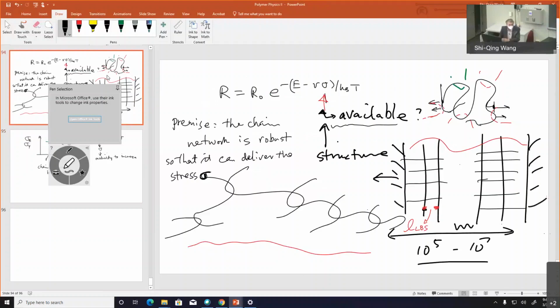to recognize that's not enough, asking us that we must worry about a structure, gives us the opportunity to identify what is that structure. In other words, to explicitly say what is the role of the chain network. Explicitly. Not throwing a word of entanglement, saying, oh, somehow we know something has to happen for ductility to occur. In fact, indeed, we know when your ductile polycarbonate, your ductile PET is made of lower molecular weight, it won't be ductile.